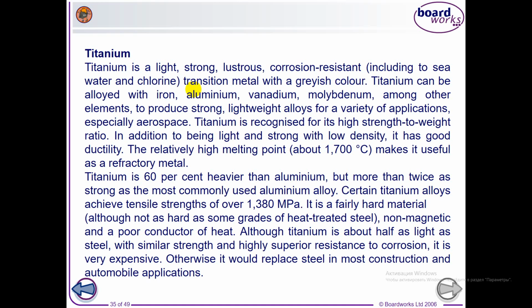The relatively high melting point, about 1700 degrees, makes it useful as a refractory metal. Titanium is 60% heavier than aluminium, but more than twice as strong as the most commonly used aluminium alloy. Certain titanium alloys achieve tensile strengths of over 1380 megapascal. It's a fairly hard material, although not as hard as some grades of heat-treated steel.